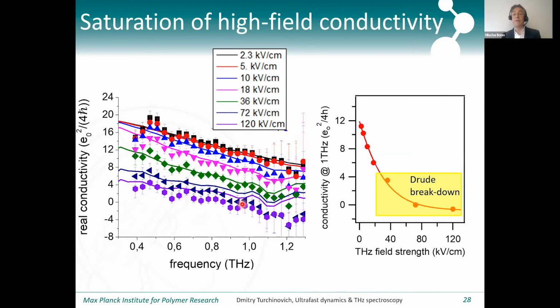But this explains why the graphene-based devices are limited to a few hundred gigahertz, because when you apply these fields, you still have some conductivity. But if you go to even smaller gate lengths, higher fields, higher frequencies, the conductivity really dies.